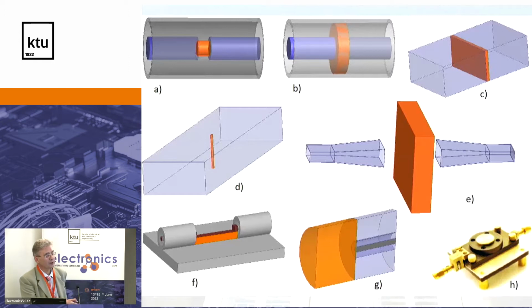And this method is very good, but you need to make a ring. That's a shortage of this method. If you go to higher frequencies, it's really complicated. If you have a waveguide, you can close it and measure the full cross-section of the waveguide. And again, measure reflection and transmission, and from that extract the parameters.